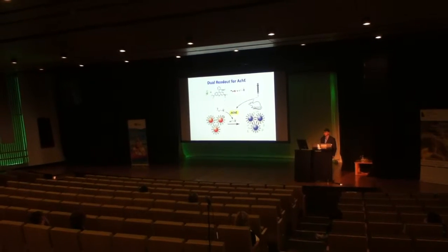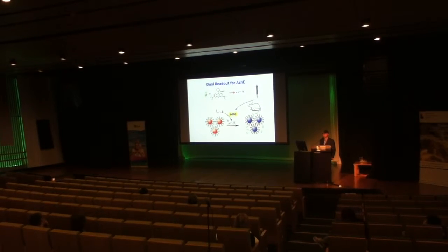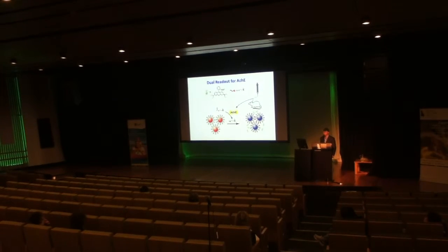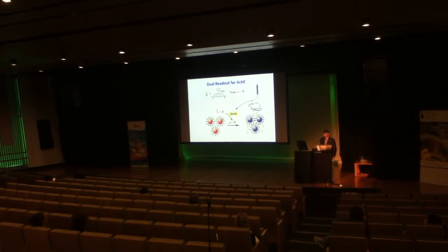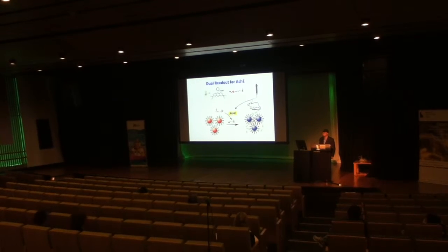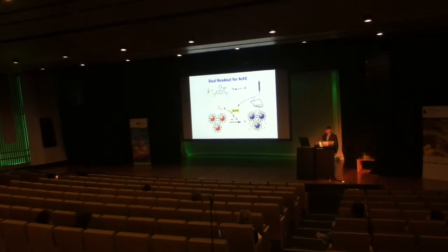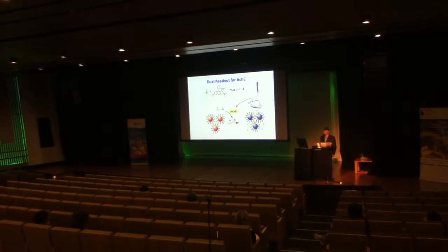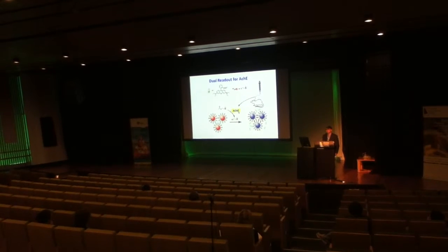So 2 things will happen after this replacement. One is the quenched fluorescence of the rhodamine will be released. Thus, we will see fluorescence in the solution if we are looking at fluorescence. The second thing is because initially the highly charged rhodamine allows the gold to be completely dispersed in the aqueous solutions. But after we do this, the gold nanoparticles will start to aggregate. So the second event you will see is that the color of the solution under white light will actually change from pink to blue.